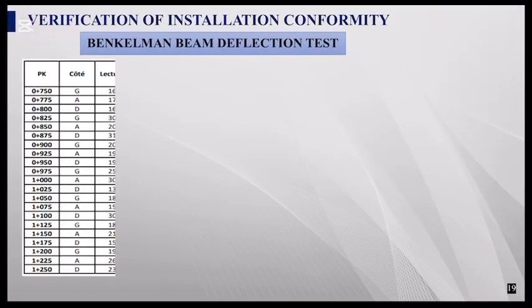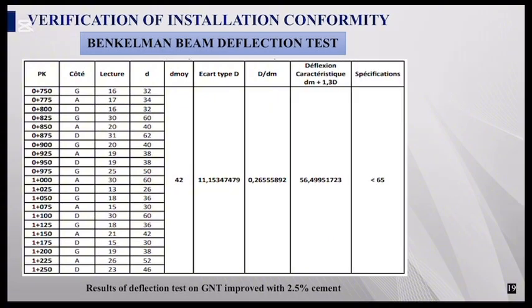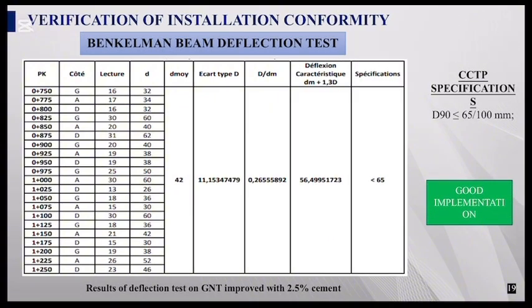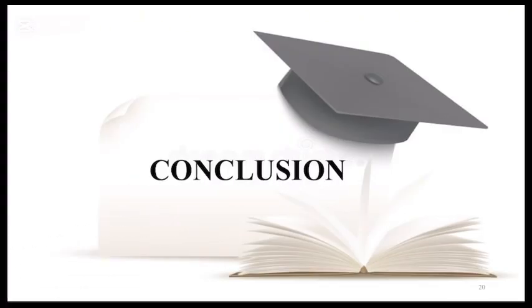The deflection test is an in-situ test used to measure the structural rigidity to resist a rolling load, to determine at each kilometer's profile the vertical displacement of the point on the surface generated by a rolling load on the ground. In our case, we found a characteristic deflection of 56, which is less than 65, which complies with the specification. This training course on the Alada-Mississento Road reconstruction site was a very enriching learning experience and helped